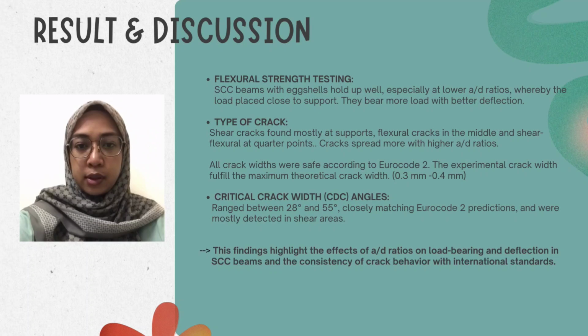For the flexural strength testing, SCC beams with eggshell hold up well, especially at lower A/D ratios, whereby the load is placed close to the support and the beam doesn't look affected by deflection. For the type of crack, shear cracks are found mostly at supports, flexural cracks in the middle, and shear-flexural cracks at quarter points. The cracks spread more with higher A/D ratios.